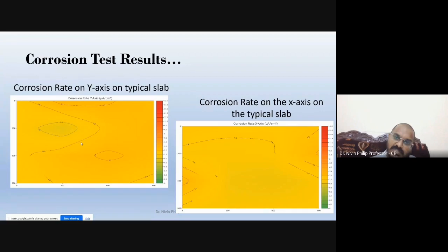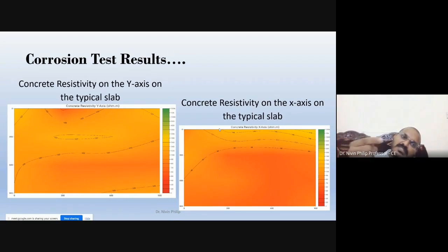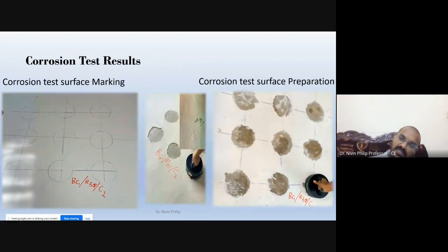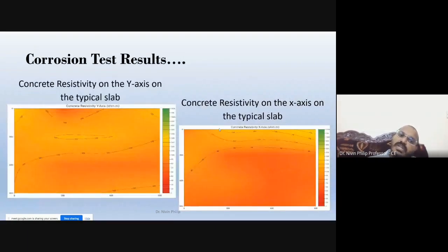But when you go for a half cell potential, the issue is that either corrosion has happened and we have to remove the concrete, or no corrosion has happened. In this case, we can identify what percentage of corrosion has happened. This is the y-axis. This is the x-axis. The only difference is that one measures the long span reinforcement and one measures the short span reinforcement. And this is the concrete resistivity. Simultaneously, the same equipment can measure the concrete resistivity also. Concrete resistivity means whether the cover concrete has the quality to resist corrosion.